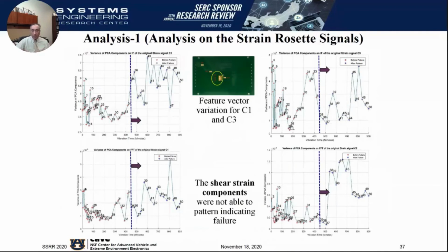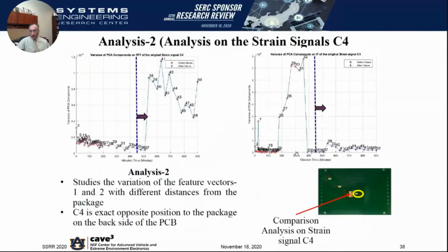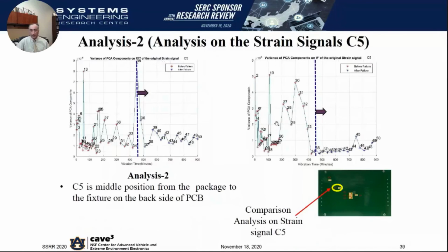So in the spirit of full disclosure, we are sharing with you what worked, but also what didn't work. Analysis 2, we looked at normal strains again. So this is C4 again. If I start to look at single sensors at slightly different locations, here the instantaneous frequency in our analysis and testing was the more robust feature vector formulation as compared to the FFT based. So here the FFT based feature vector fails, but the IF still succeeds. So that's the advantage of using the IF based PCA.